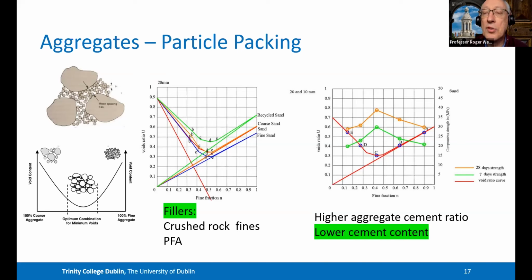And on the right-hand side, you can see in the orange graph that this does indeed deliver better strengths. The better the packing, the better the strength. And if you don't need the extra strength, then maybe you could do with less cement. So in other words, increase the aggregate cement ratio. You can still end up with the strength you wanted and have the durability you wanted, provided you don't go below the required minimum cement contents.